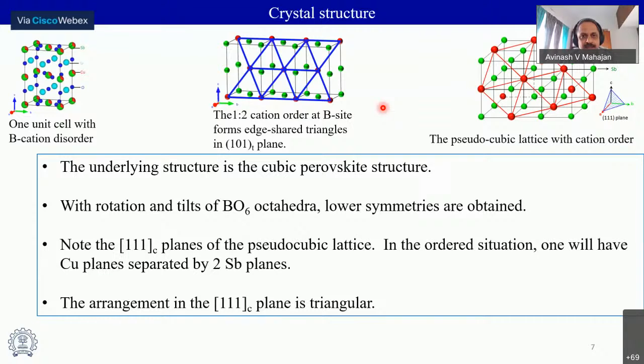And then one has the site ordering, and then one can get a triangular geometry if one looks at the 1-1-1 planes. In the usual disordered situation, there is no triangular geometry, but if you look at the pseudo-cubic lattice, then one can get a triangular geometry in the 1-1-1 planes. And actually, we have evidence from superlattice peaks in the X-ray diffraction of this 1:2 cation ordering at the B site from copper and antimony. So the only magnetic atom here is spin-half copper.